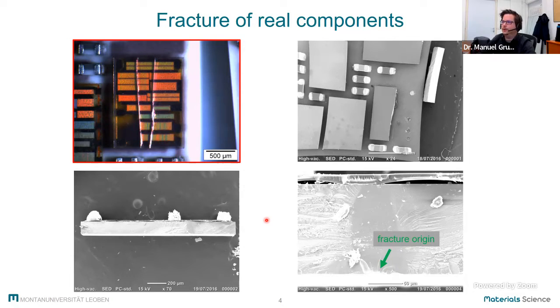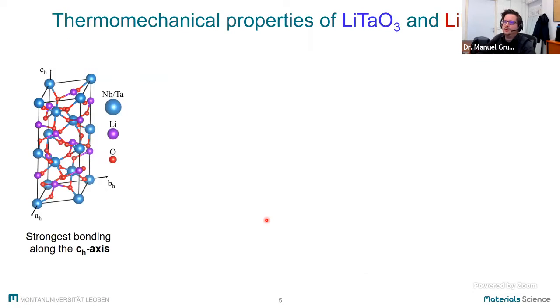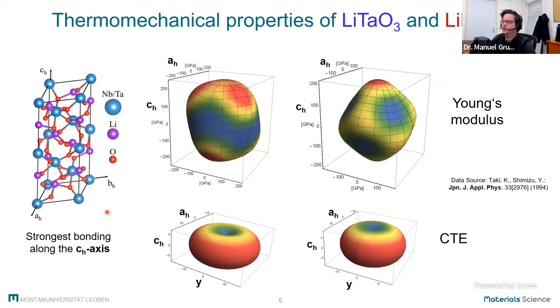Therefore, we had to take the material properties, and especially those of the single crystalline materials are strongly dependent on the micro scale, so on the unit cells. We see here the unit cell for lithium tantalate, it looks the same for lithium niobate. And if we have a look onto Young's modulus and coefficient of thermal expansion, we can see that the strongest atomic bonds are aligned along this C-axis.